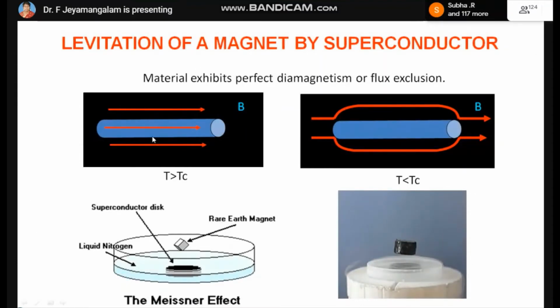You have a material kept in the magnetic field. So the flux lines are passing through this material above the critical temperature. When the temperature is reduced, the flux lines are expelled out. Can you see this one? With the normal field, the flux lines are expelled since the material has become a superconductor. In the third picture, you have a specimen which could act as a superconductor, and when liquid nitrogen is poured into the vessel, the material will become a superconductor. At that time, when we bring a rare earth magnet to it, the magnet will be repelled by the superconducting material because it will expel the magnetic flux lines.